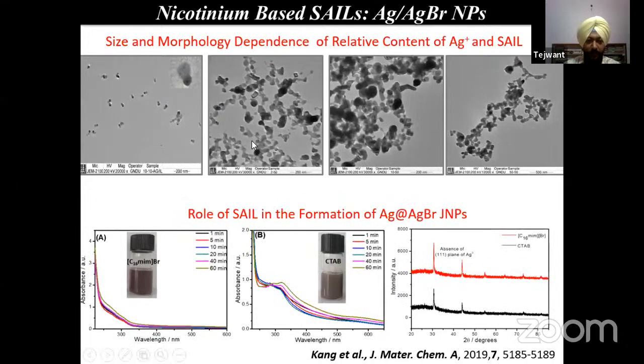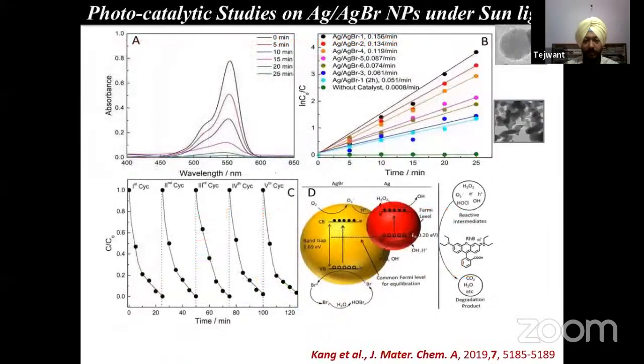We have also proved how the relative content of silver ion and SAIL affects the morphology of the nanoparticles formed, and what is the specific role of surface active ionic liquid in the formation of silver Janus nanoparticles. It has been found that no silver bromide Janus nanoparticles could form if we take some imidazolium based ionic liquid or a conventional surfactant, cetyl trimethyl ammonium bromide. So it is established that the nicotinium based ionic liquid is very much necessary for the preparation of such nanoparticles. The prepared nanoparticles have been utilized for the photo reduction of rhodamine B.